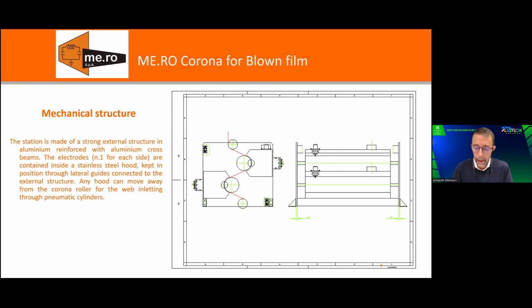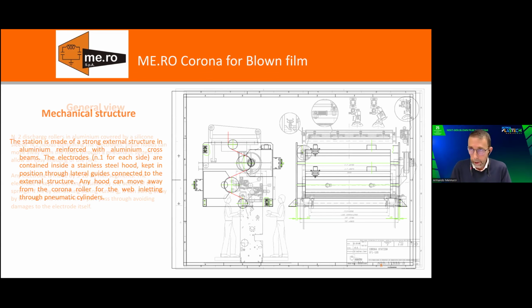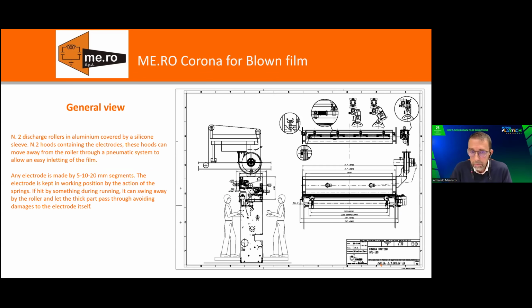The corona rolls are in aluminium normally, covered in silicone sleeve or vulcanized silicone rubber, and very rarely, I would say, for blown film lines, we have also done some applications with ceramic coating for the corona rolls. As for the electrodes, most of the time the electrodes on a blown film line are segmented electrodes. So we supply segments of 5, 10, 20 millimeter, or even 3 millimeter under special request.